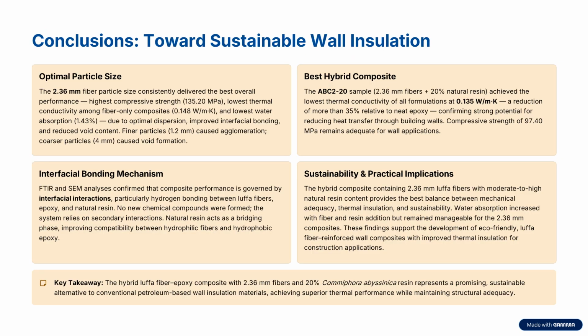that the best hybrid composite, the ABC2-20 sample, achieved low thermal conductivity, a reduction of about 35% compared to the epoxy, and also a compressive strength of 97.4 MPa, which remains adequate for wall applications.